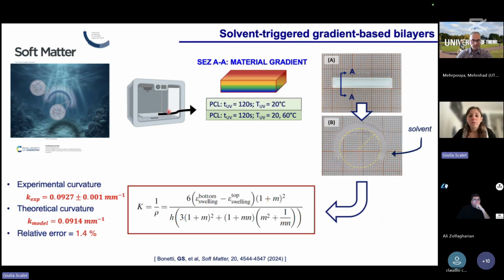This technique was also very interesting because it allowed us also to obtain self-folding structures upon immersion in solvent, thanks to the material gradient within the thickness. So in particular, we use again this network, and we print different layers of this material using different cross-linking parameters. And this allows us to obtain a material gradient along the thickness that bends upon immersion in the solvent. And this bending can be also supported with the classical, very easy beam theory, starting from the Timoshenko theory, that can show essentially good results in terms of accuracy.